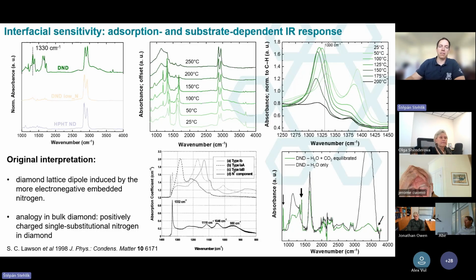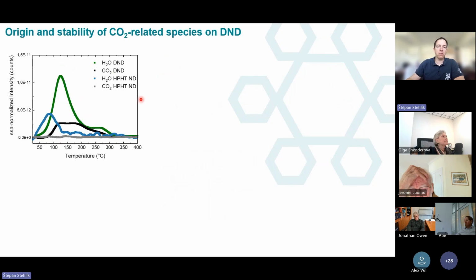So then we further confirmed the presence of the CO2 by mass spectroscopy, by the desorption study. So the green, and also of the water. So on DNDs, the green signal is the water signal. You can see that the desorption occurs at about 150 or a little bit less. But then we have some second contribution, and simply some water is present up to 300 degrees C.